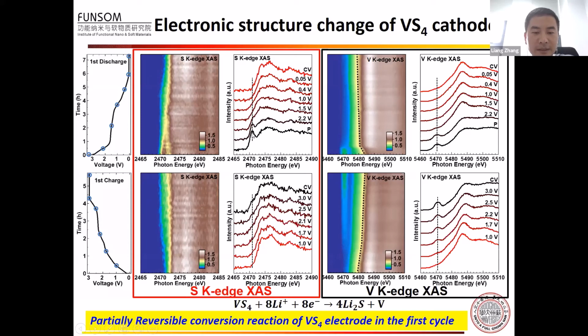So here for the sulfur K-edge spectra, the main feature is at 2471 eV. This feature is the hybridization between sulfur 3p and vanadium 3d states. And during the discharge process, the intensity of this feature gradually decreases.